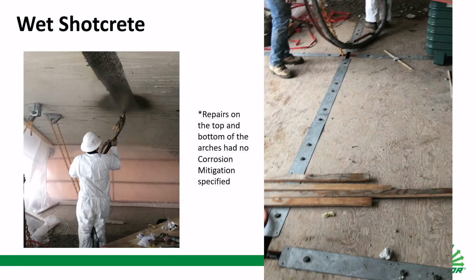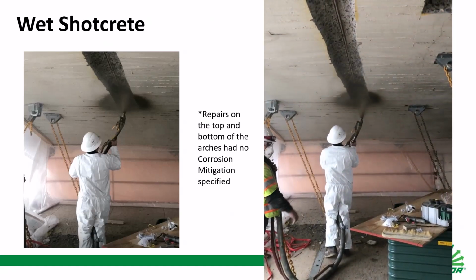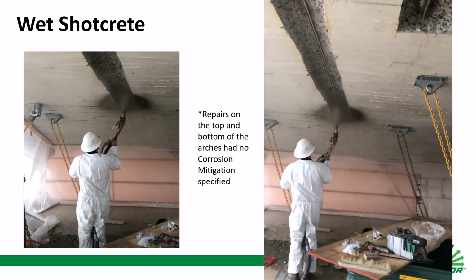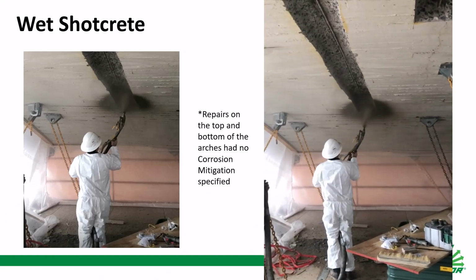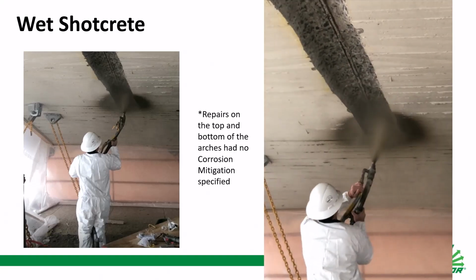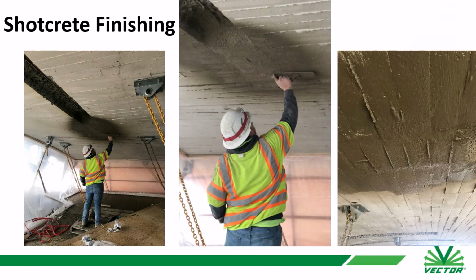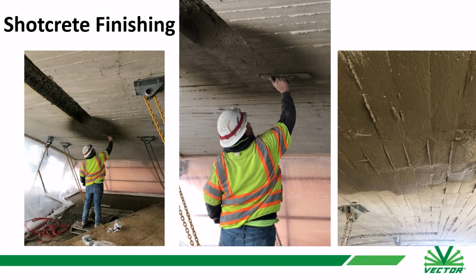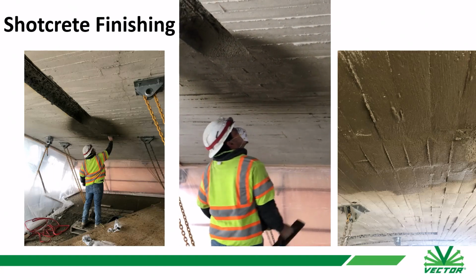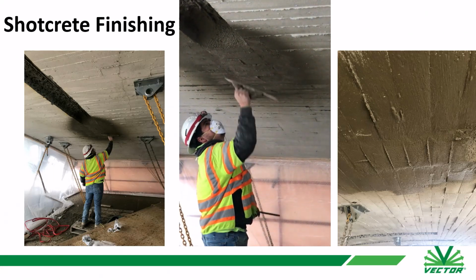And as part of this, it doesn't have as much to do with the corrosion, but it's just interesting. They used a wet shotcrete material. I don't know if you've ever seen this in action, but you kind of see it being sprayed on. You basically have the wet mortar being flowed through the nozzle, and you have a burst of air that's spraying it onto the surface. And the nice thing here was that because it was historical, they were trying to recreate the board form finish as well with the shotcrete. So you had to have some skilled technicians to do that.